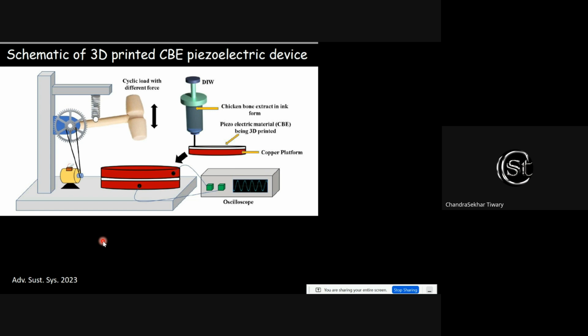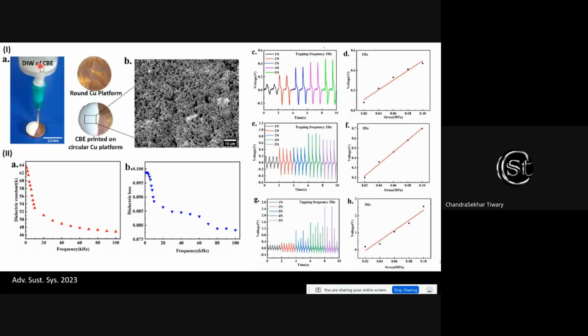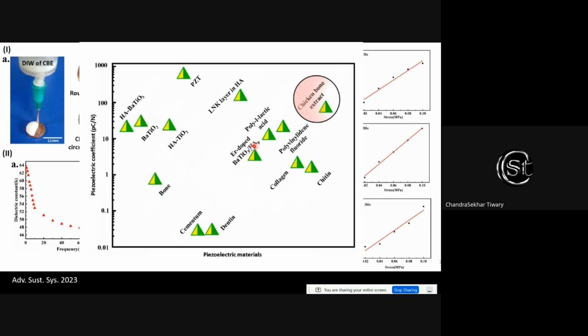Also, this chicken bone particle can be utilized in an energy harvesting device. So what we do here, we take the chicken bone extracted particle, we call it CBE, which can be printed on a substrate, and copper is the substrate we utilize, coat it, and then we start putting force. Now, once you put force, we see that they start producing voltage. When we did a detailed study, we calculated and observed that the piezoelectric coefficient of this chicken bone extract particle is comparable to some of the conventional piezoelectric materials like barium titanate or PZT and so on.